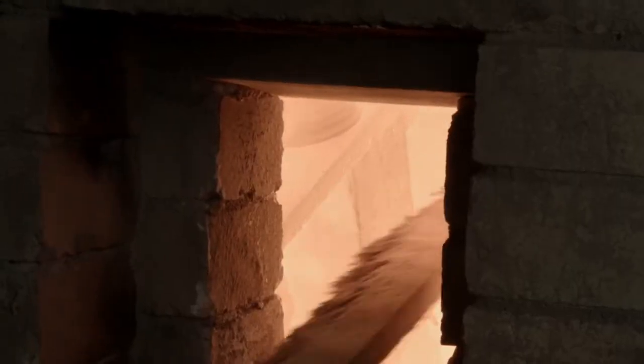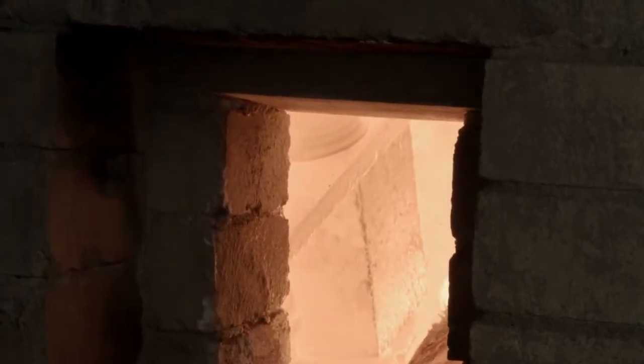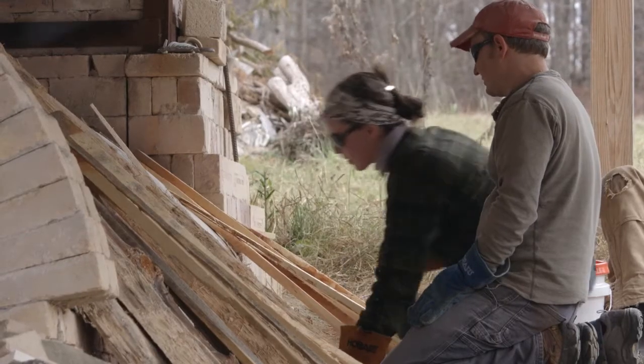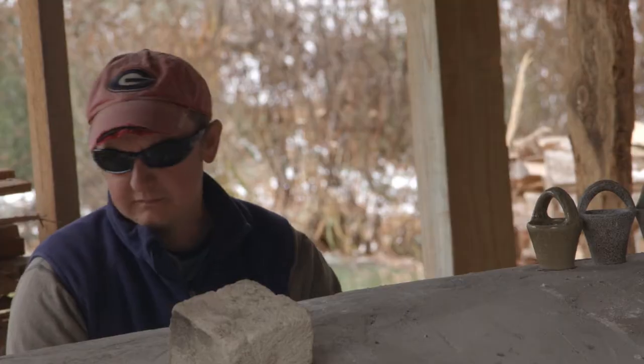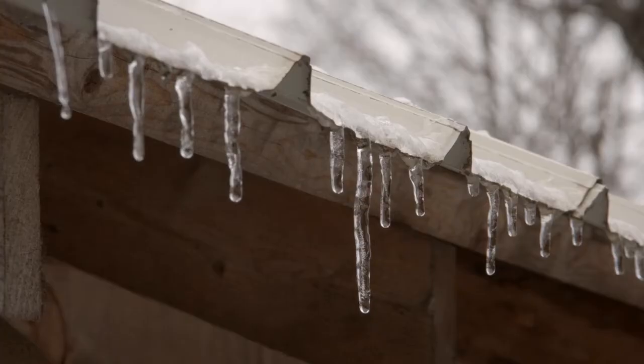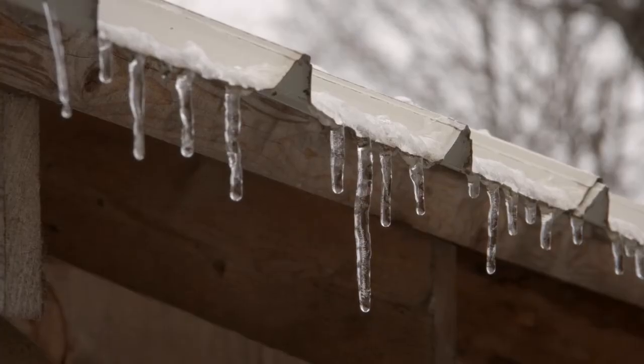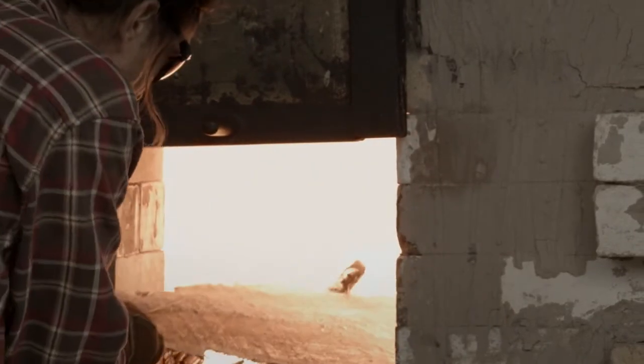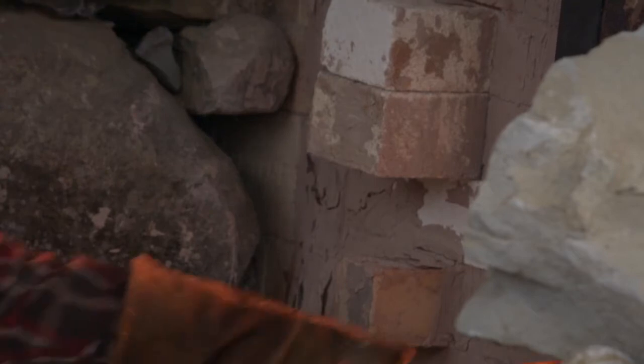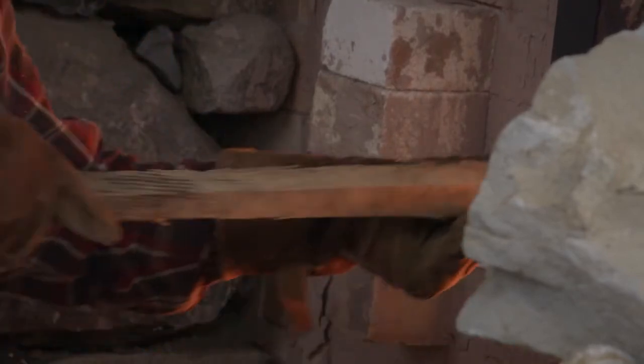I then move to the back of the kiln and start firing the sides, introducing wood actually into the ranks of pots that are set from the outside while they're maintaining temperature up front. It's called sidestoking, and what that's doing is pulling the heat back to raise the temperature throughout the entire kiln — a 15-foot stretch.